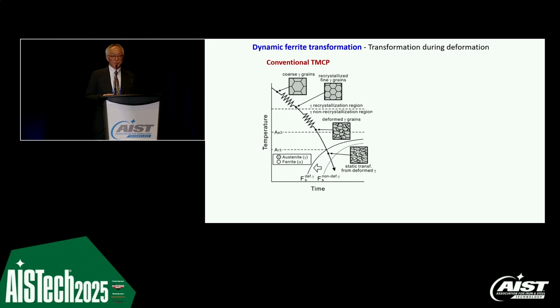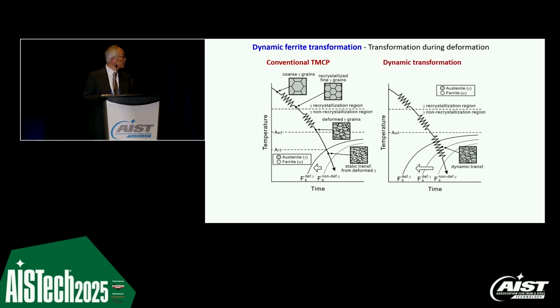Dynamic transformation is transformation during deformation. This is typical TMCP. Of course, we have the deformation in the recrystallized region of the austenite and the non-recrystallized region of the austenite, and then cooling down, we have the transformation. However, when we look at dynamic transformation, we have further deformation below the transformation temperature.